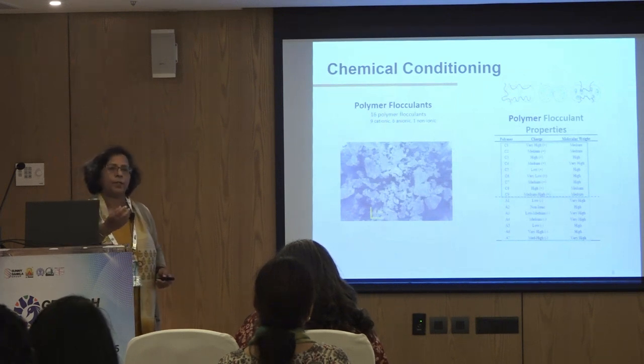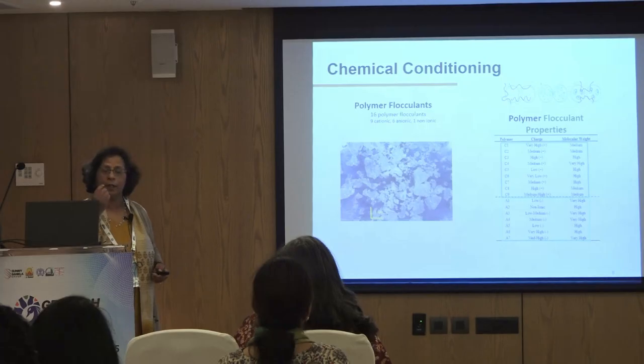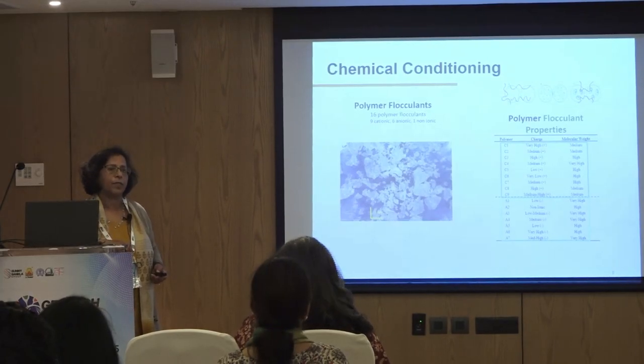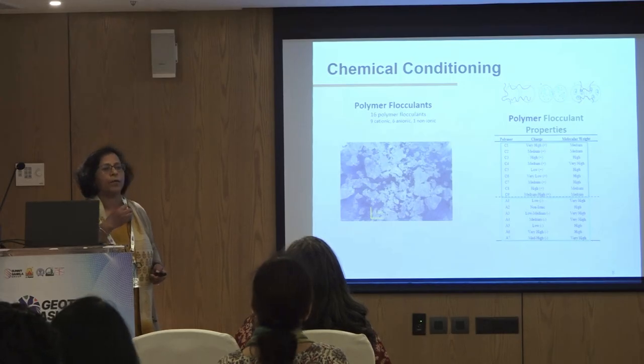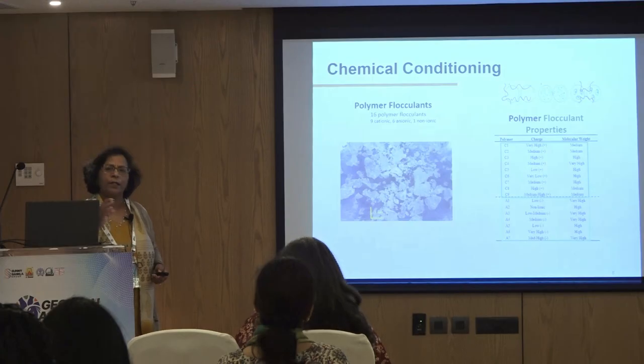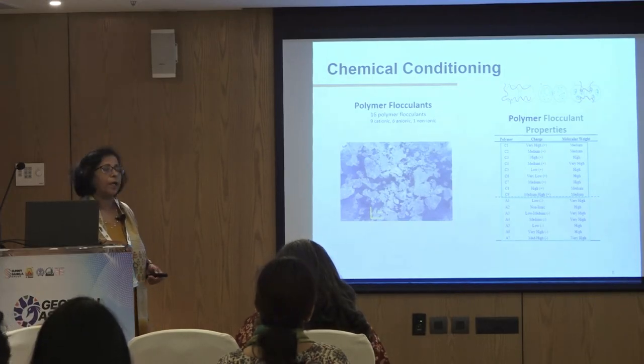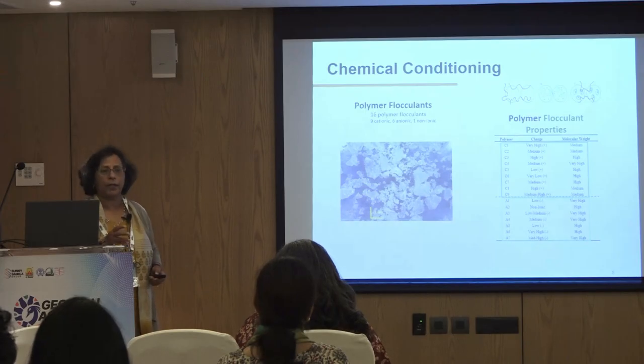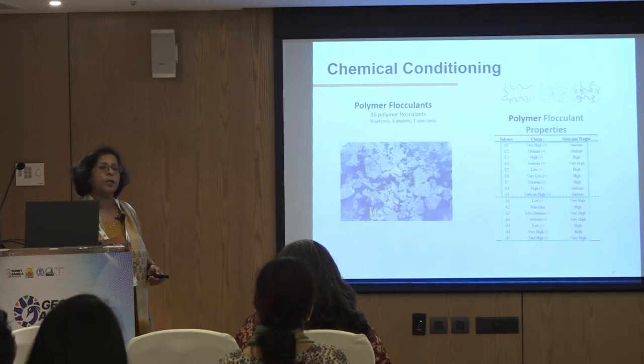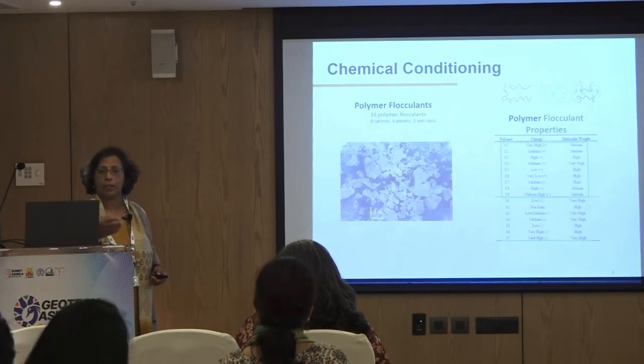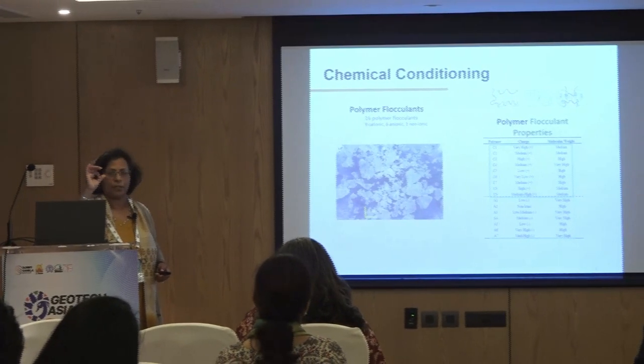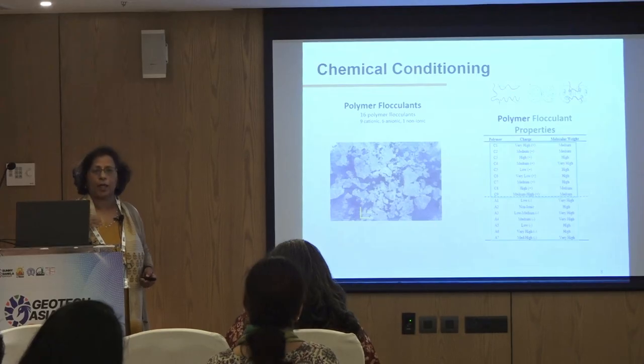Now, generally, these sediments have a significant amount of fines, and when they are pumped into tubes, which are quite open, woven geotextile, they need to be flocculated, otherwise a lot of fines will come out. So in 99% of projects, polymers are added, and these polymers are typically polyacrylamide, ranging from cationic to anionic. So we selected a number of polymers, and for each sediment found out what is the best polymer which can make the particles lump and flock. So now you have a larger particle, it's not a particle anymore, it's a flock, which can be retained on geotextile when we dewater.